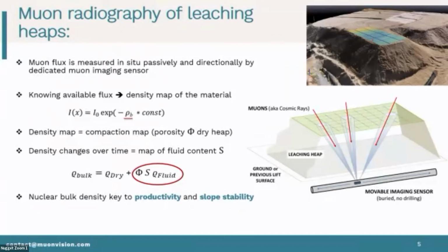All right, so let's now focus on leaching operations. The measurement would occur like this. You place a muon imaging sensor under the asset, under the region. The region is the patient, and the sensor is the detector. The sensor has to be able to not only measure the arrival, the passage of the cosmic ray muons, but it also has to be able to determine their direction. And once you do that, you essentially measure the cosmic ray muon flux at depth. And we have just argued that you can transform this into a density map of the material, which is really the leach pad.